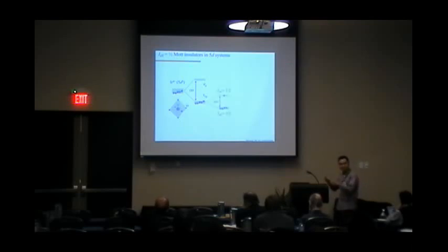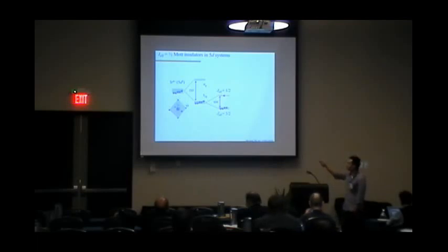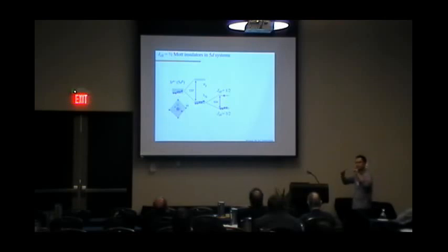You turn on now strong spin-orbit coupling, and what happens is that the t_2g's get further mixed into these J effective 1/2 and 3/2 levels. The 3/2 get filled. The 1/2 is half filled, so this looks like a half-filled single band model. And because of spin-orbit coupling, this J effective equal half band is actually very narrow. And so moderate amounts of on-site Coulomb interactions are sufficient to open up a charge gap. Okay, so you get a situation that's akin to what models of cuprates look like.